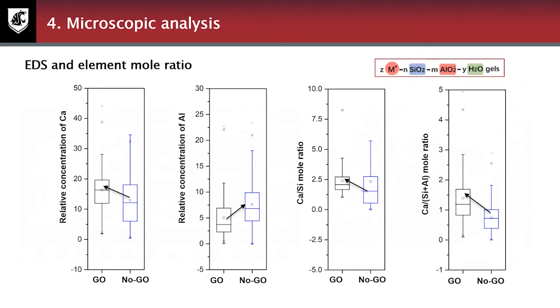Based on the SEM results, we also do the EDS analysis. Here we mainly focus on some key elements, for example, the calcium and the alumina. We can say that after adding graphene oxide, the relative concentration of calcium was increased, but the relative concentration of alumina was decreased. Based on the relative concentration, we calculated the molar ratio of calcium to silica and calcium to silica plus alumina. And we find that both these two molar ratios were increased after adding graphene oxide.